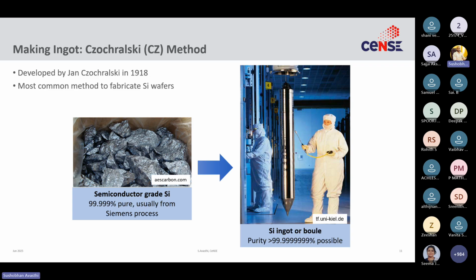Now, the way they make these is they basically melt it and slowly pull out a single crystal ingot. So this is a polycrystalline material. It doesn't have any specific orientation. The lattice grains are all over the place. This is a single crystal material, ultra pure, usually weighing several tons. And then they take this ingot and do further processing to make the wafer. The reason the wafers are circular is because these ingots come out circular. They come out cylindrical.